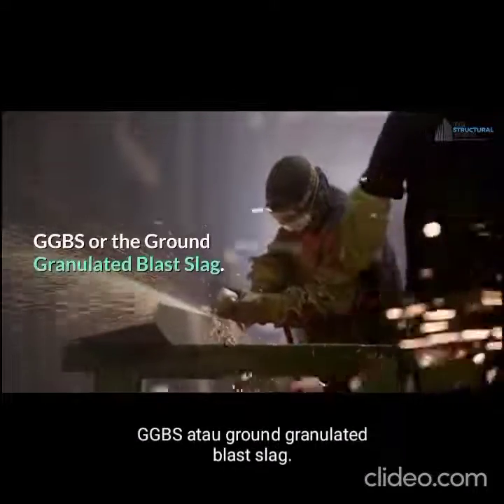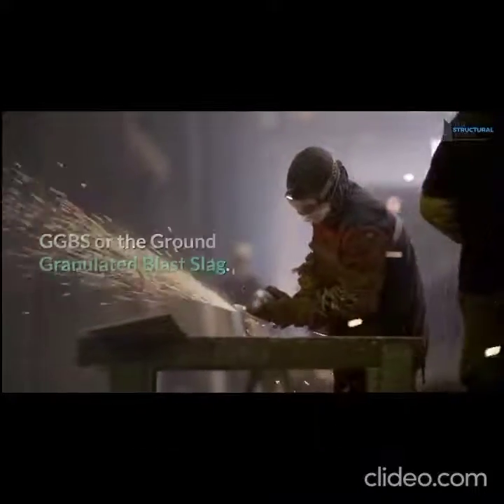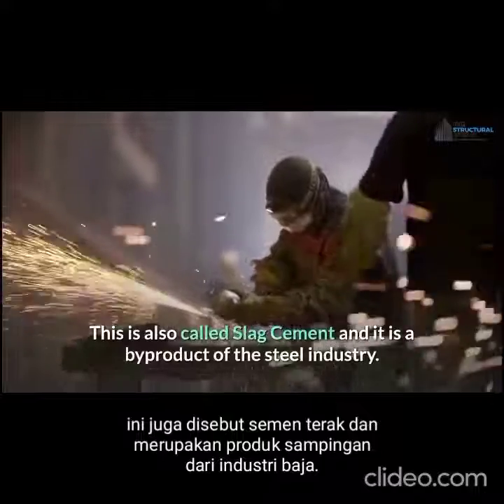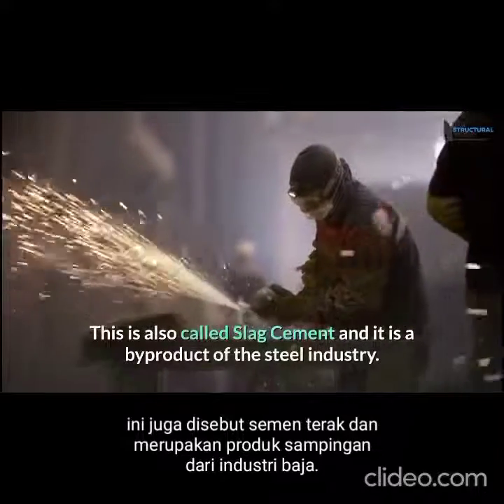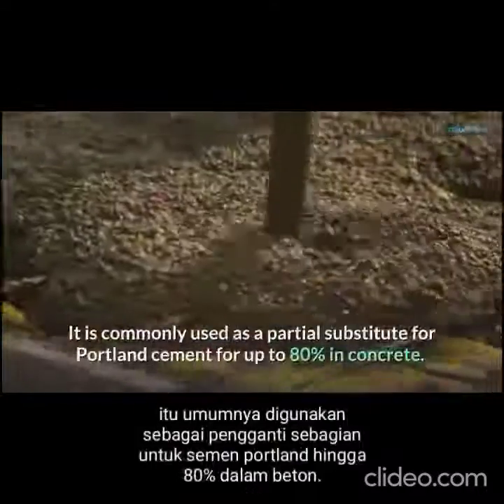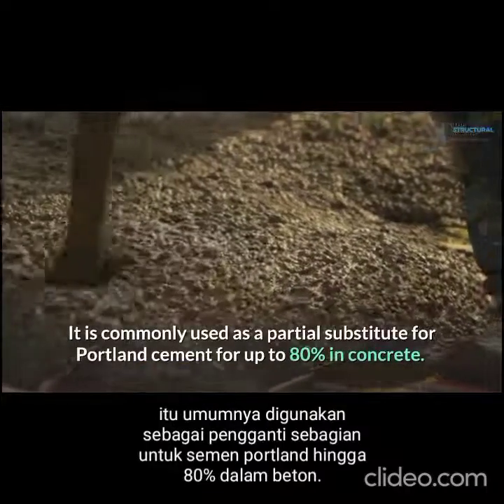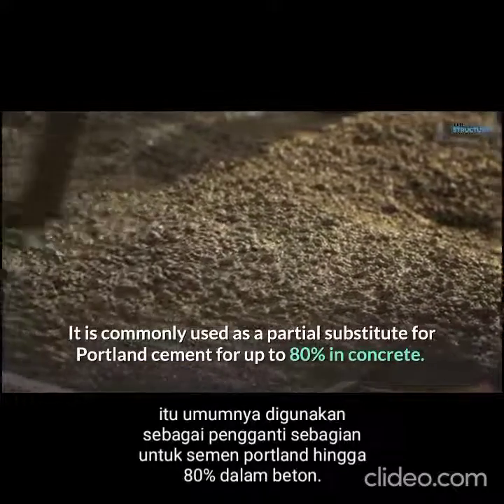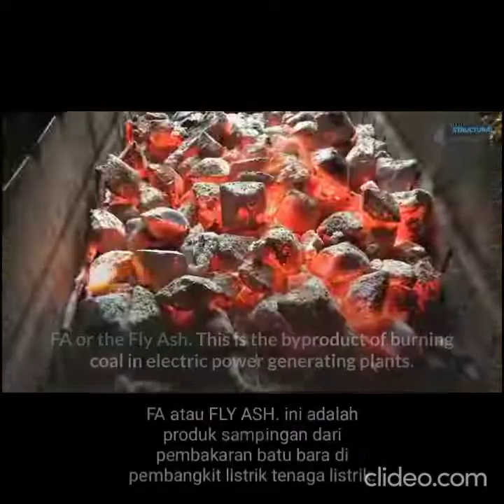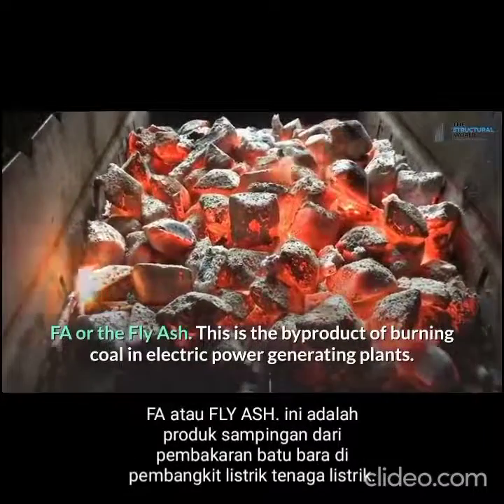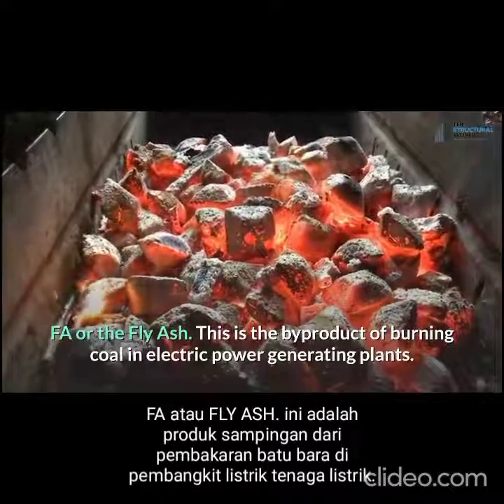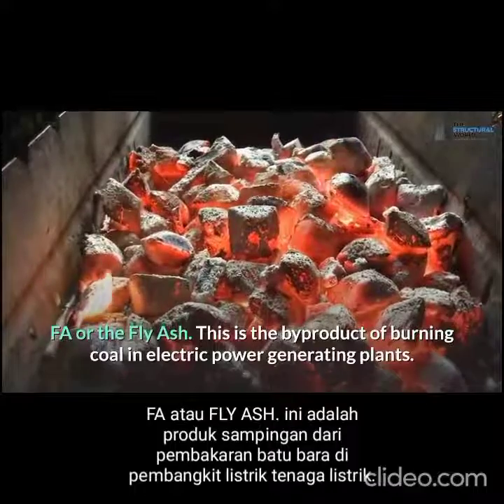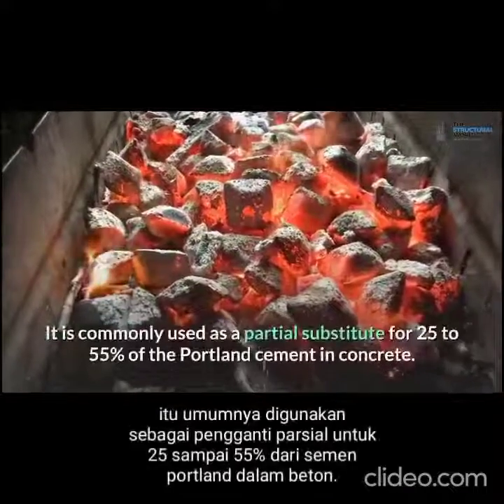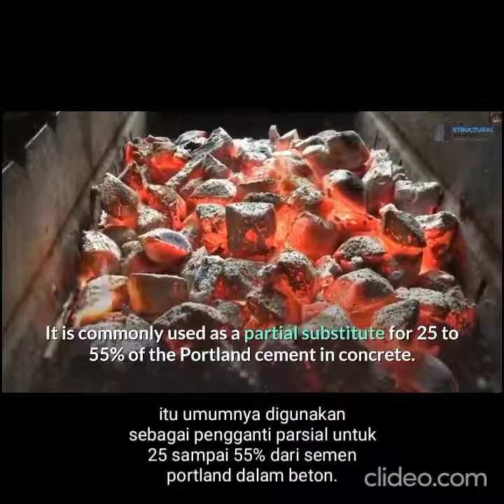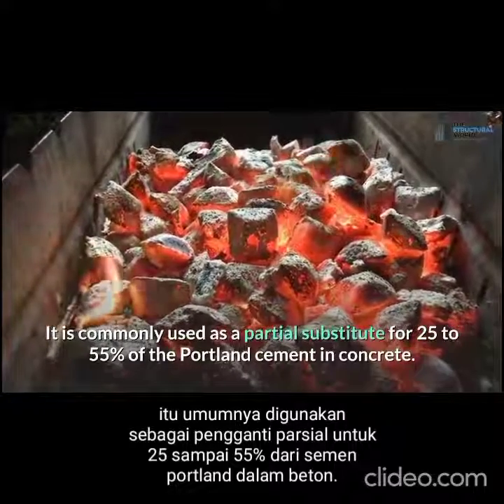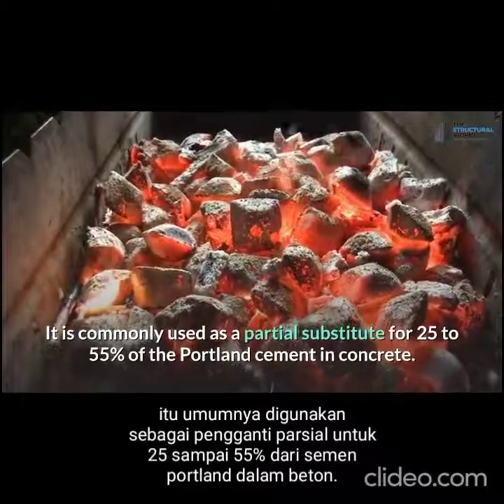GGBS, or ground granulated blast slag. This is also called slag cement, and it is a byproduct of the steel industry. It is commonly used as a partial substitute for Portland cement, for up to 80% in concrete. FA, or fly ash. This is the byproduct of burning coal in electric power generating plants. It is commonly used as a partial substitute for 25 to 55% of the Portland cement in concrete.